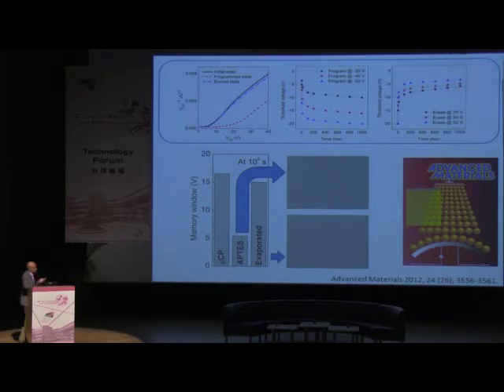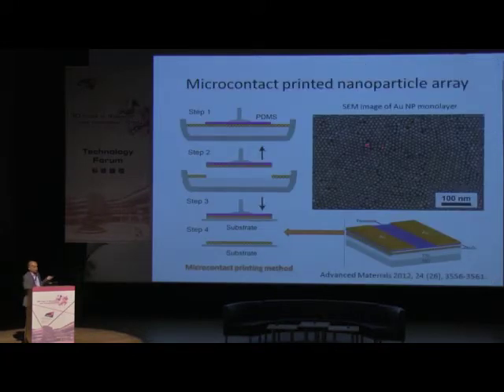Then we try to understand how these nanoparticles compare with a film, or using a substrate dipped into the solution to self-assemble the nanoparticles. So we just try to compare. Now, what's the beauty of these devices? Each particle can hold charges. Our conventional devices all form a film. So when you have a film, when the charges are trapped inside the film, they can always leak laterally. So there are two kinds of leakage. One is lateral leakage, and another one is vertical leakage. But if we have a defined layer of particles in a particular monolayer, these charges are confined in each and every nanoparticle. So basically you don't lose them. This is the beauty of this nano floating gate.